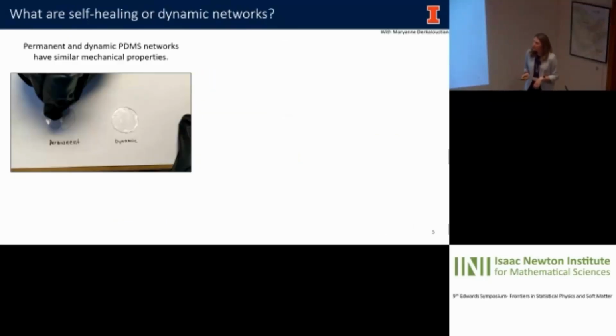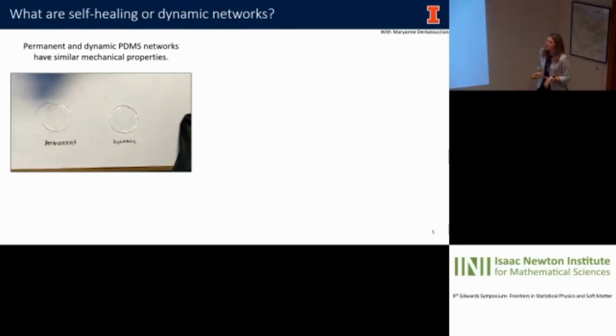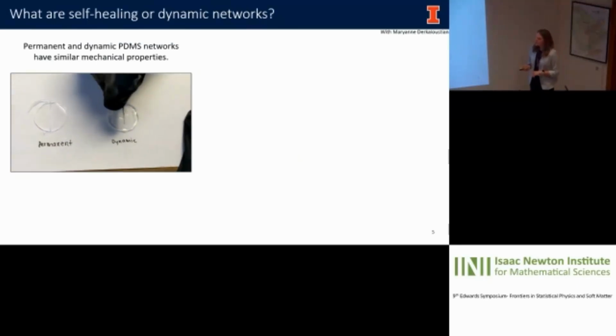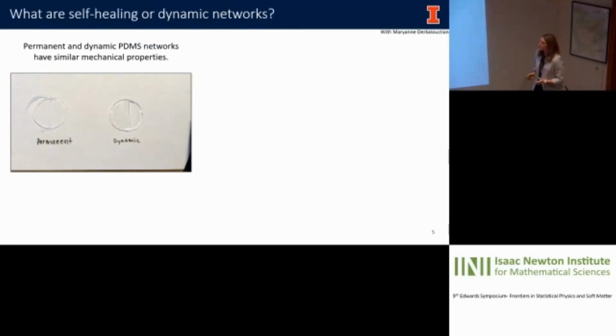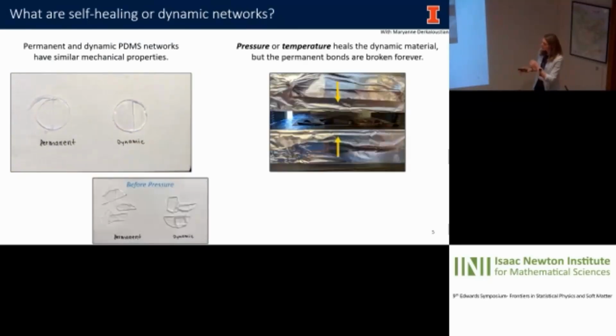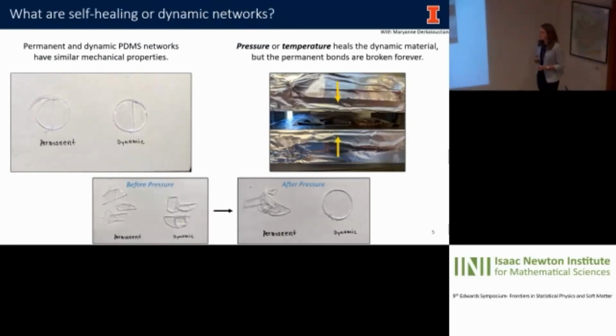Now, what do I mean by dynamic networks? As in the video here, you can see that PDMS with permanent bonds versus PDMS with dynamic bonds looks qualitatively similar. But then when I apply pressure or temperature, the material with the dynamic bonds is able to go back into the shape of the mold that I put it in.